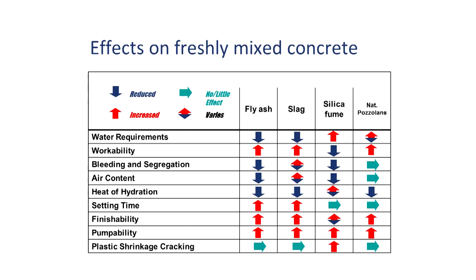Again, the way pozzolans work is they need calcium hydroxide to be activated. They don't do anything on their own. Calcium hydroxide is generated as the cement hydrates. That takes time, so nothing happens instantly. And the more pozzolan that replaces cement, the less cement there is to generate calcium hydroxide. And it takes a certain concentration of calcium hydroxide to kickstart that pozzolan to turn into the calcium silicate hydrate gel.